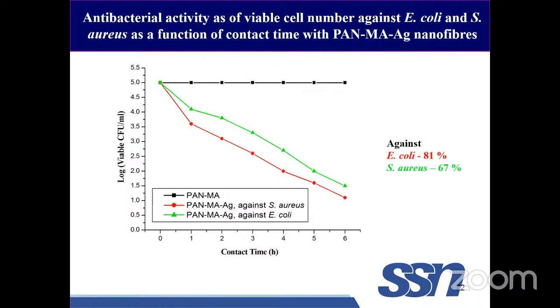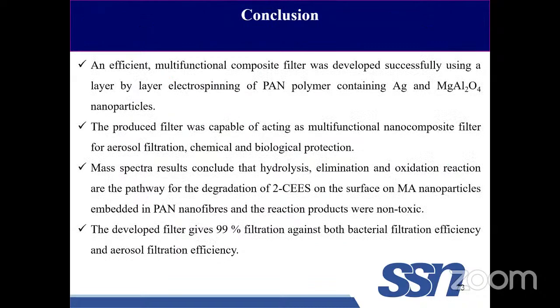As I already mentioned, it is not only going to filter, it is also going to act against the biological agent and chemical agent. The chemical agents are being filtered and degraded to 95%, whereas for bacterial agents, we tested against both gram-positive and gram-negative bacteria. As you can clearly see, 81% of the gram-negative and 67% of the gram-positive bacteria are killed in the viability study. So we have developed a multifunctional filter which can be utilized for military purposes, and a common person can also use this filter to protect against these ABC agents. We found 2-CEES was degraded by hydrolysis, elimination, and oxidation. The prepared filter gave us 99% filtration efficiency against both bacterial agent as well as aerosol agent.